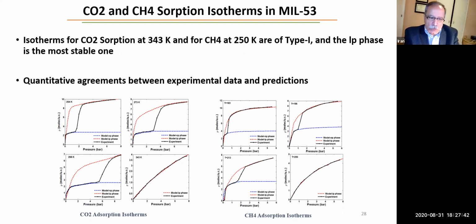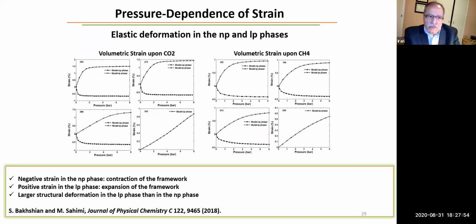Here we are showing CO2 adsorption and CH4 adsorption isotherms, and the transition between the two is also correctly predicted at various temperatures. In addition to that, we can calculate displacement, as I mentioned. So we calculate strain versus pressure. Again, at the bottom of the figure, you see the narrow pores. The strain is negative, which means that they have contracted. At the top, you see the large pores, which is basically the expansion of those pores. So you will see both of them, and with one model, we can predict all of it. This was published in 2018.